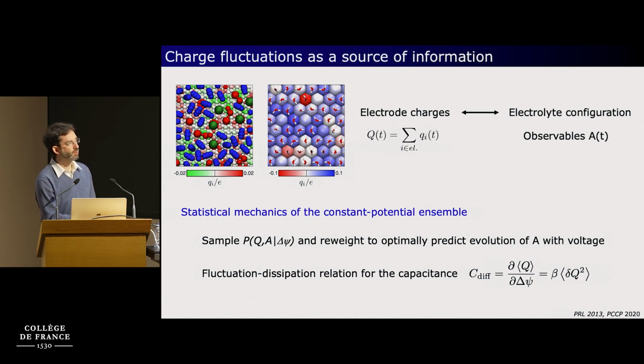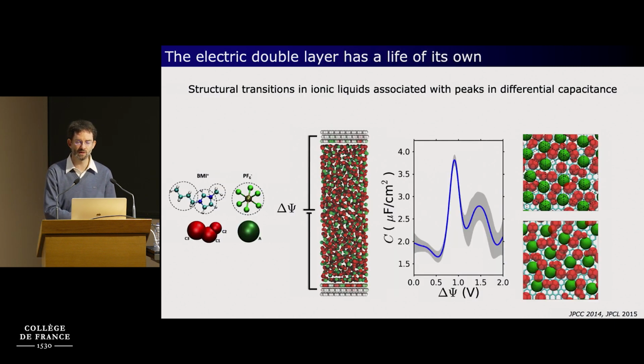It is in fact equal to the variance of the charge distribution. So you look at the equilibrium charge fluctuations, take the distribution and its variance, and multiply by beta, which is the inverse of the thermal energy. And this gives you a measure of the differential capacitance. And we've used that to investigate structural transitions in ionic liquids.